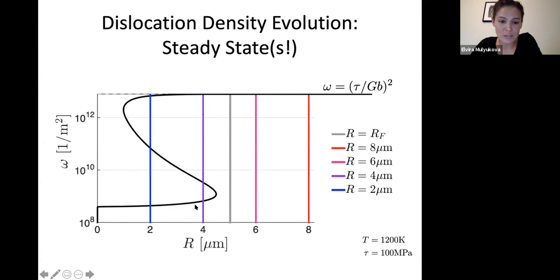And so if your grain is growing from a dislocation poor state, the first steady state that we'll encounter, and which will be stable, is a much lower dislocation density. So the takeaway message from here is that, taking into account various sources and sinks for dislocations, the dependence of the steady state dislocation density may not only be on stress, as you would see for larger grains or materials deforming predominantly by dislocation creep, but may also have a dependence on grain size for finer grain material. And those steady states would be at a smaller dislocation density.